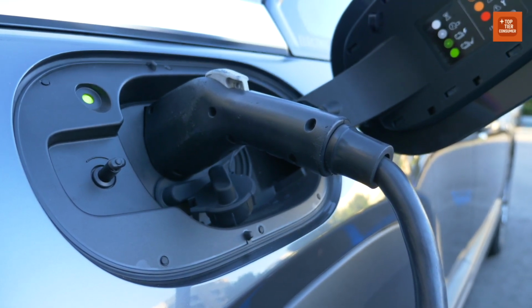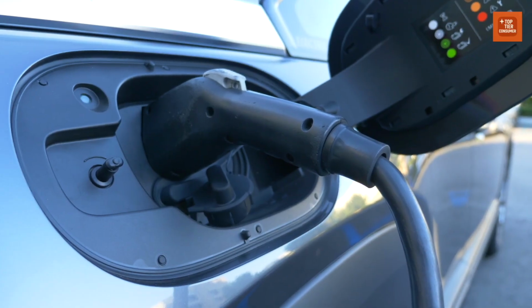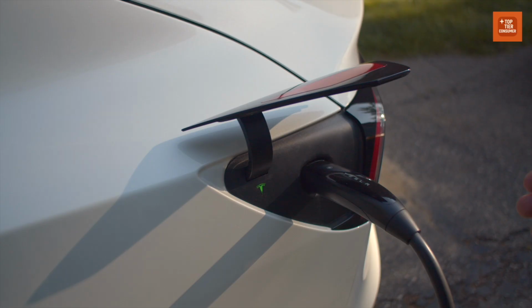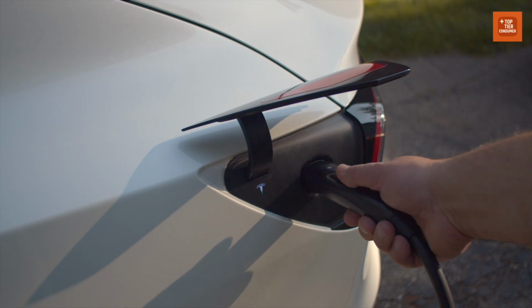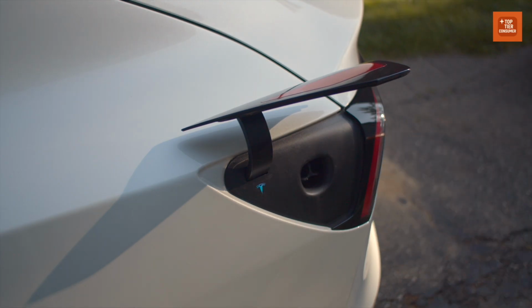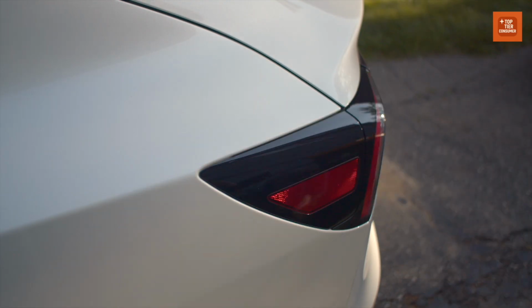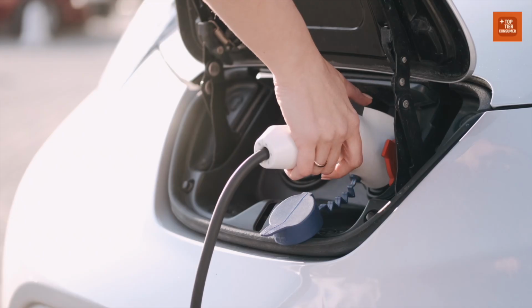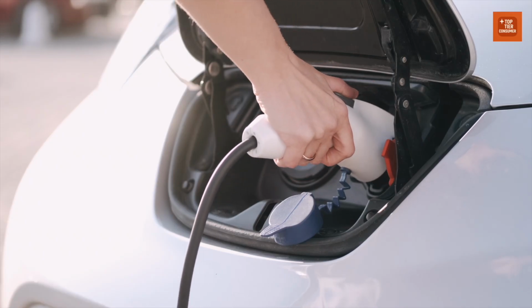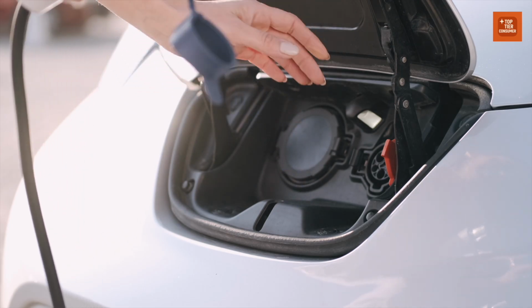A recent study reported a corrosion-inhibiting liquid electrolyte for lithium metal cells that tolerated aggressive fast charging in lab conditions, suggesting that careful interfacial chemistry can unlock both longevity and speed. While that result is not a drop-in car pack, it shows the physics can be bent in our favor.